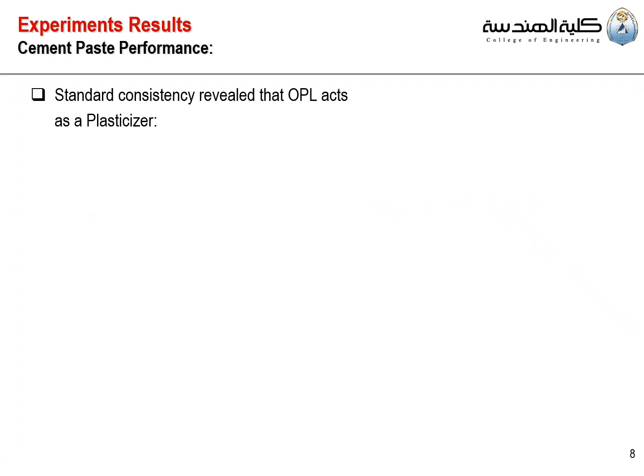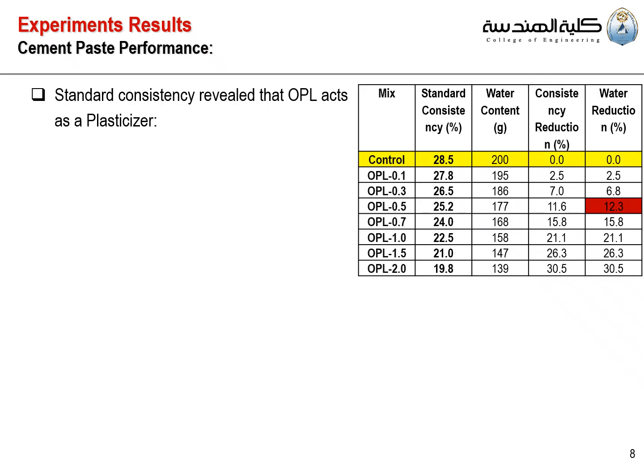Experimental results. First, we will present the cement paste performance. So here we have two tests. The first one is a standard consistency test, which revealed that OPL acts as a plasticizer. And as you can see from the table, the control base has a standard consistency of 28.5. This is typical for the type of Portland cement we use.